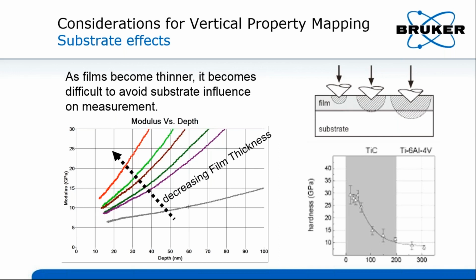Typically, the 10% rule is a general approximation for the film's intrinsic mechanical properties. That is, we will collect the small depth data with the penetration depth smaller than 10% of the film thickness. As the films become thinner and thinner, the elastic deformation reaches the substrate at very shallow depths, and it can be very difficult to make measurements without any substrate influence.